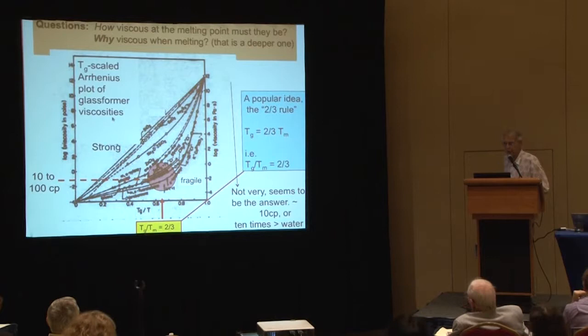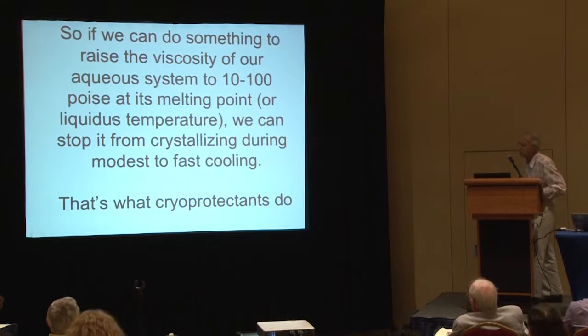So if we can do something to raise the viscosity of the water by either pressurizing it or adding stuff to it, just enough to get the viscosity up to 10 to 100 times its normal viscosity, then we'll be able to stop the crystallization from occurring during moderately fast cooling, and that's of course what cryoprotectants are supposed to do.